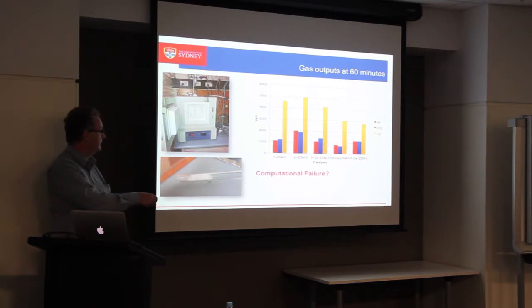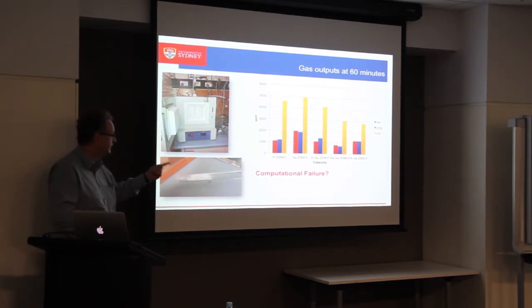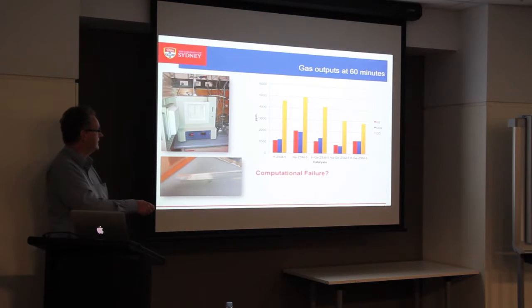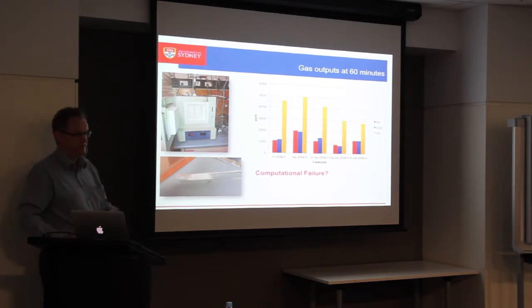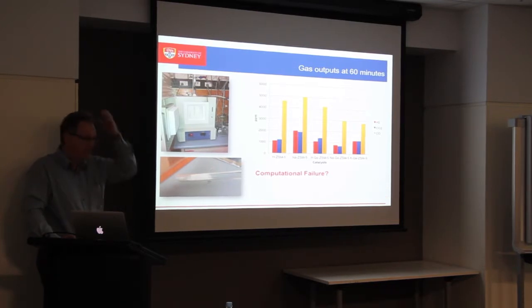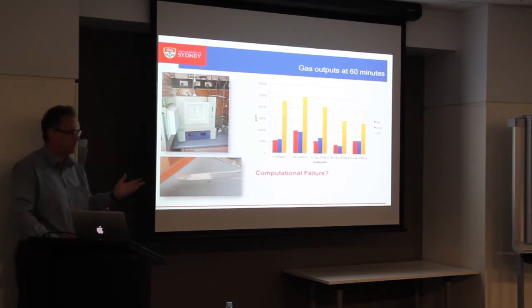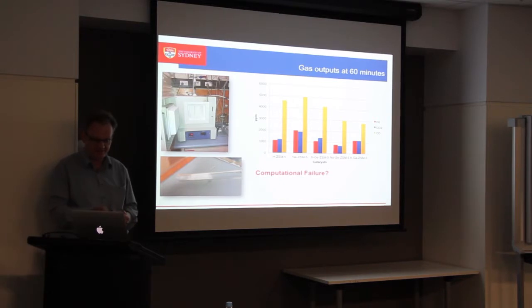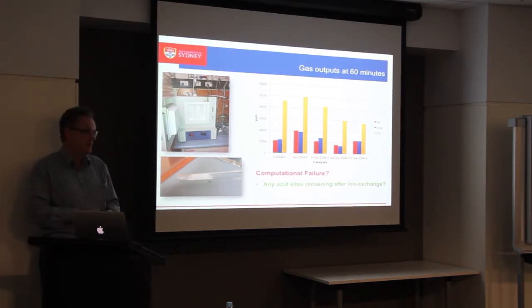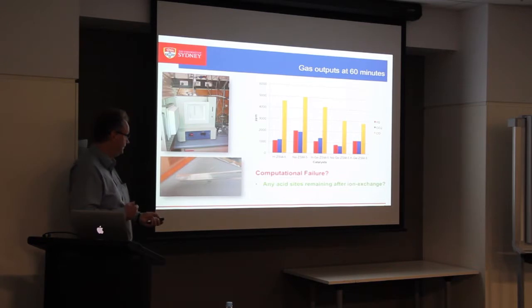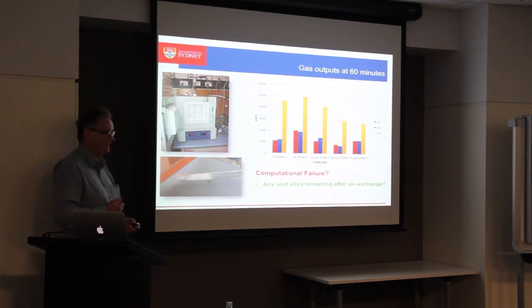Remember, I said this thing was expected to be quite selective — one pathway going one way, the other going the other way. But if you have a look, there's virtually no selectivity. Basically we're dehydrating, and we see that by all the CO that I'm generating. So what I've just told you turns out to be completely wrong. Is it a complete computational failure, or catastrophic computational failure?